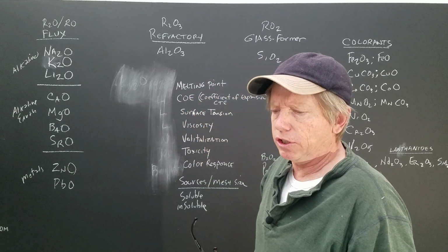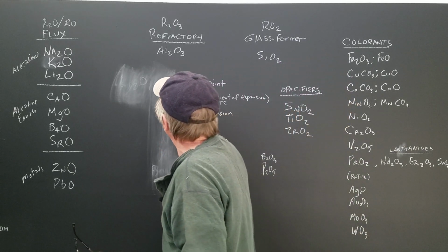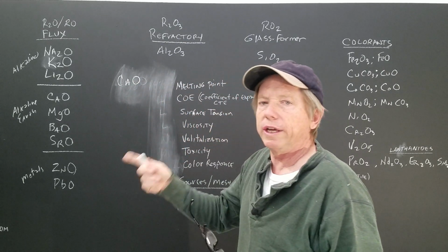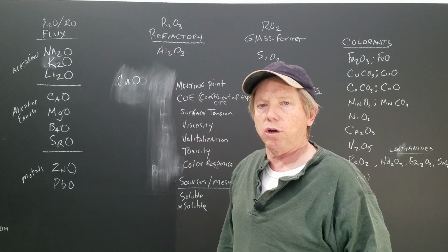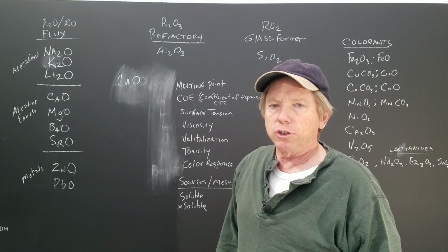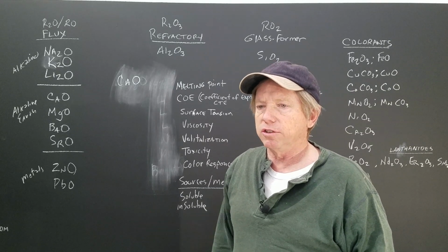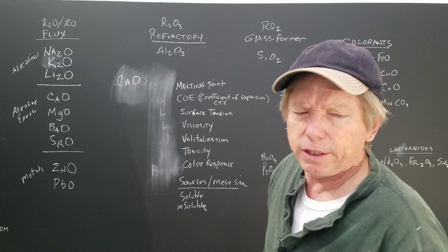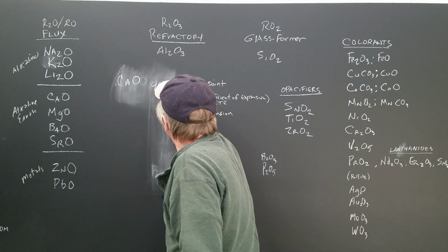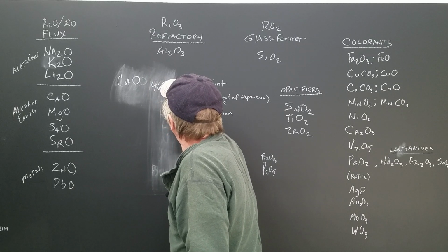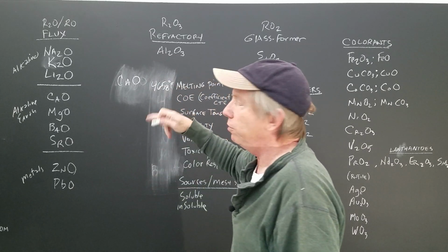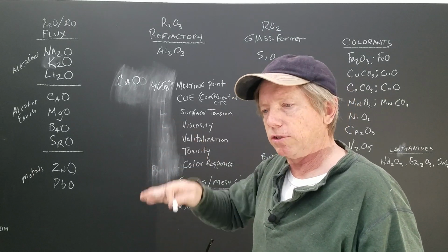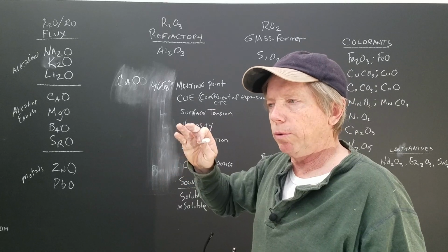Now what we need to do is to do calcium. Super good material for glazes. It's in almost all glazes at all temperatures. It makes strong glazes, great for functional glazes like celadons and stuff. It makes strong surfaces. Its melting point is very hot. But it forms a eutectic with alumina and silica, which is the classic eutectic in ceramics, which brings it down to about 2100 to melt.